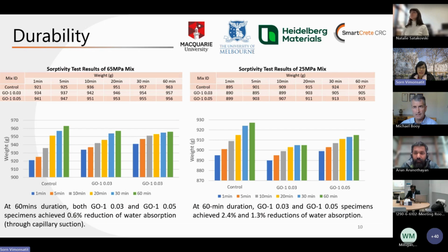The next one is another test that we've conducted, a sorptivity test. You prepare the samples, submerge part of them in water, and then check the rate of water absorption by measuring the weight of the sample. Looking at this graph, with the control and different time intervals, the control shows quite a steady increase in water absorption, whereas with the graphene mix the trend is slower. The rate of water absorption and weight increase is slower and dropping as time increases. So you can see the benefit of having graphene inside the concrete is also to limit the sorptivity or water absorption, which means it reduces the permeability of concrete.